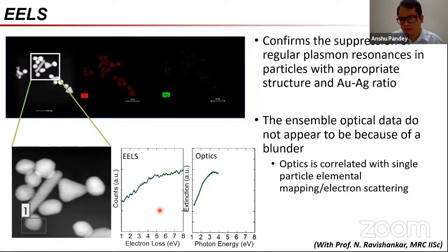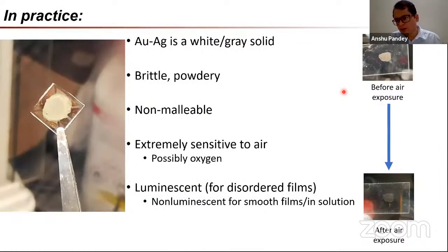So with that, we have this unusual picture of this material, where all of a sudden we have suppression of regular plasmon resonances, but more importantly, suppression of loss inside the material, even at fairly high energy, which is really strange. This is really, really strange and worrying. Before I go to why it's worrying, let me say what this looks like in practice. In practice, this material reflects what is already being said. It's a white or grayish white solid. It's extremely brittle and powdery. These points were just raised a moment ago. It's very non-malleable.